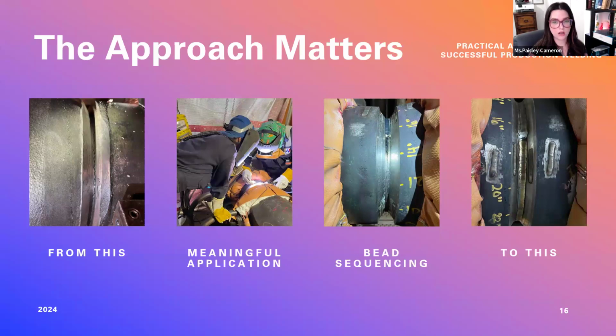This was a very interesting job. This was up in a northern region of Canada, and this is a steam methane reactor in the hydrogen production units. This particular place had a loss of containment resulting in a thermal release on another part of the plant, and they came through and did some opportunity inspections and found some through-weld cracking on some of the outlet manifolds. As you can see, it's beautiful cracking. If it was to crack, this is very beautiful welding, very beautiful crack. Unfortunately, right in the weld, which is what you don't want in that sense.